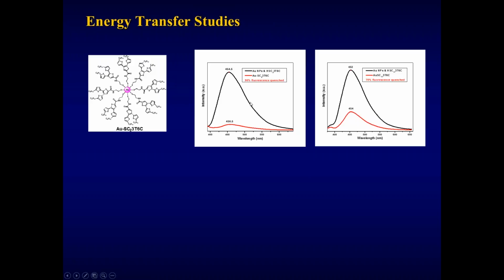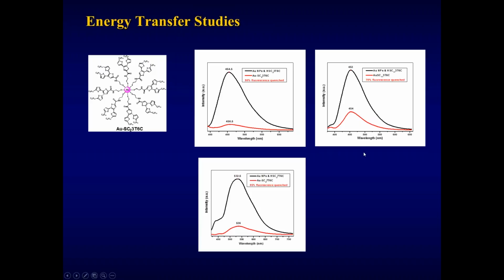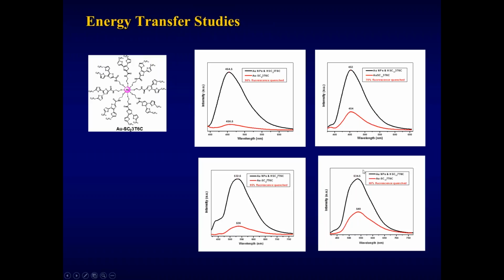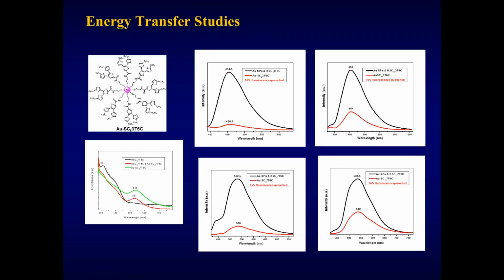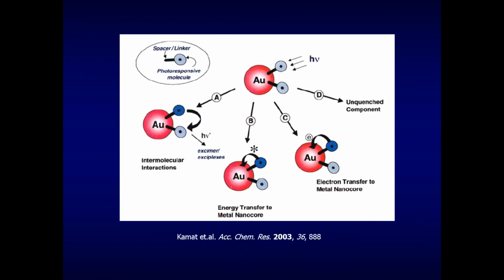Because of the proximity or closeness of the terthiophene to the gold core nanoparticle, we can have as much as 90% quenching of the fluorescence. On the other hand, when we increase the number of carbons to 11, so it changes spacer length to 11, we were able to observe only 70% quenching. Now, in the case of the 7T, where we have less overlap, we get 85% quenching and 60% quenching. So what this indicates is that the quenching mechanism is simply a function of distance from the gold nanoparticle core.